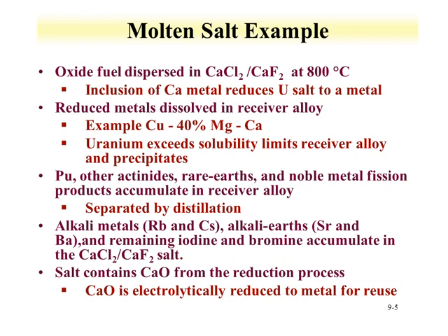And in the case where an oxide was originally used, you would form calcium oxide in the reduction process, so a direct oxide reduction can also be used. In this case, the calcium oxide would be electrolytically reduced to metal for reuse within the process, and insertion at the initial point as the reductant for the uranium.